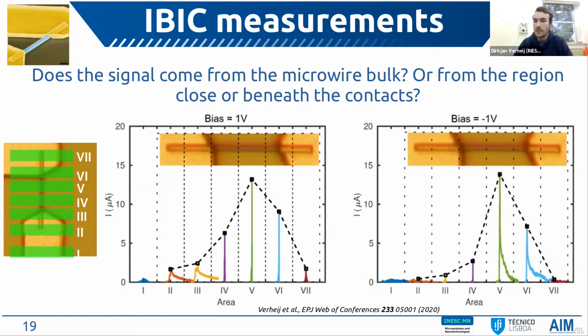One thing we have to note here is that our beam is not the most stable beam in the world, so variations in the proton flux might exist, but the fact that we observe a very good correspondence between the results at negative and at positive bias really indicates that the contact potential barriers are not influencing that much here. So the reason why we observe lower signals might be because of the metals deposited on top of the wire, but the protons should cross these metals with ease. So we're not sure why we observe this effect, but we can from these results conclude that the signal really comes from the bulk region of the wire.